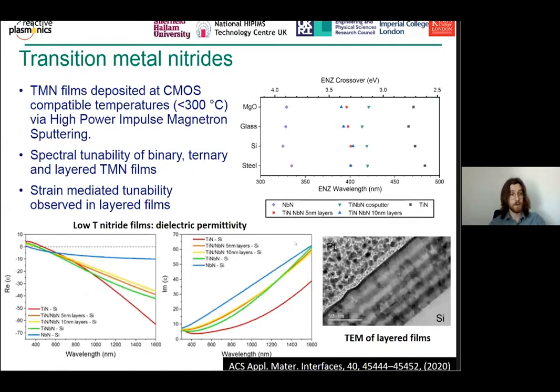Depositing at high temperatures, which we need for highly metallic titanium nitride films, is limiting in the practical inclusion of this material in CMOS fabrication process flows, or it also limits us in the patterning methods that we can use. So we aim to deposit at lower temperatures, CMOS compatible temperatures of less than 300 degrees C. And to do this, we collaborated with Sheffield Hallam University and the National HIPIMS Technology Centre to deposit titanium nitride films using high power impulse magnetron sputtering. And this produces an incredibly dense plasma with highly energetic species, and that allows us to deposit metallic films at these low temperatures.